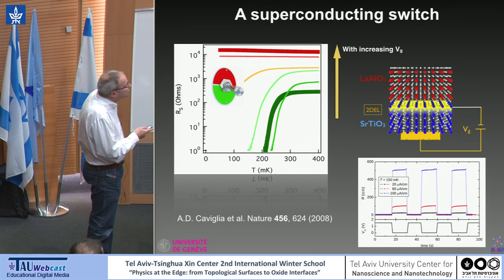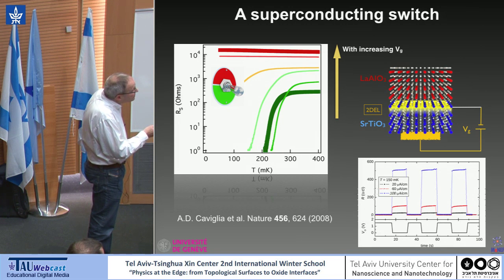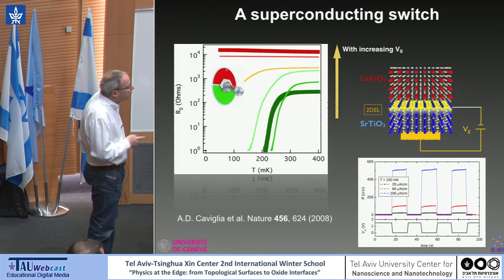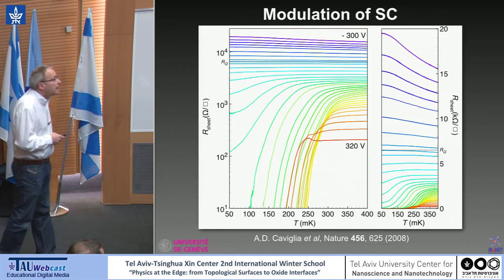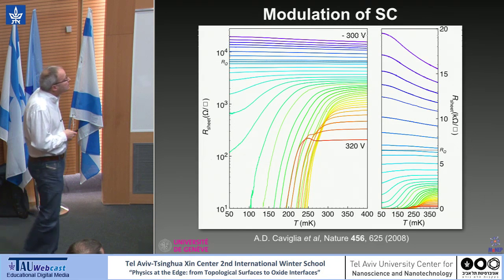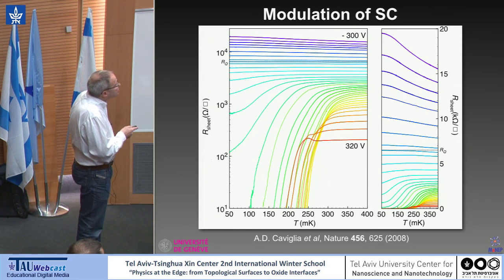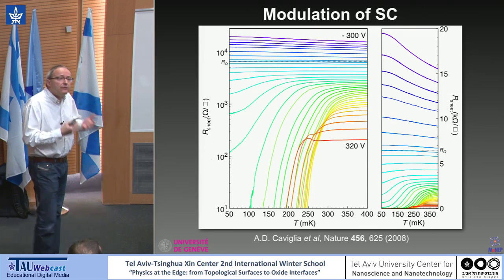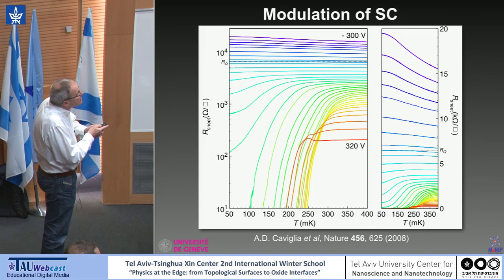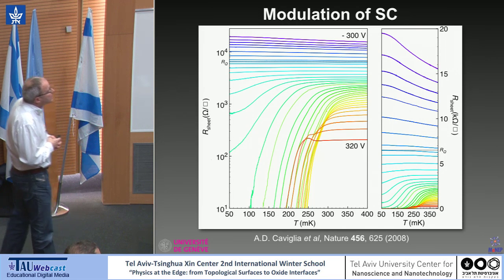You see here another experiment we performed with Johan Mannert with a top gate. You see here that the resistance is 0 for 1.5 volts. You go to 0 applied bias, the system is in a dissipative state, and you can go back and forth. We measured many of these curves and many samples, and this is in general what you see. This is the sheet resistance versus temperature, log scale, linear scale. You see that you lose superconductivity, and you move to a state which is not a very good insulator. The resistance is increasing, but maybe even saturates.